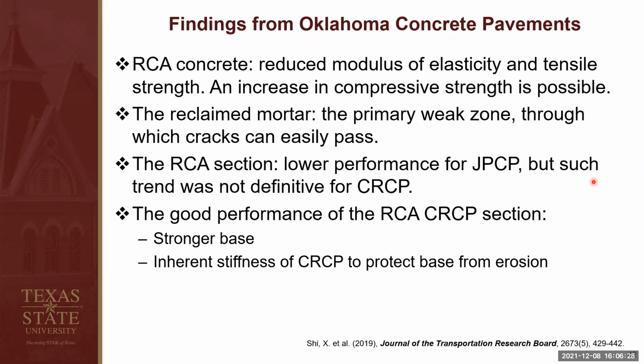So the general findings from Oklahoma concrete pavements for the RCA concrete: it has reduced modulus of elasticity and reduced tensile strength, but we did find an increase in compressive strength for the I-40 sections. For the reclaimed mortar, we believe it is primarily a weak zone, and the cracks can easily pass through the reclaimed mortar. And for the RCA field sections, we found the field section had lower performance for the JPCP, but for the CRCP, the performance was comparable with the control section.